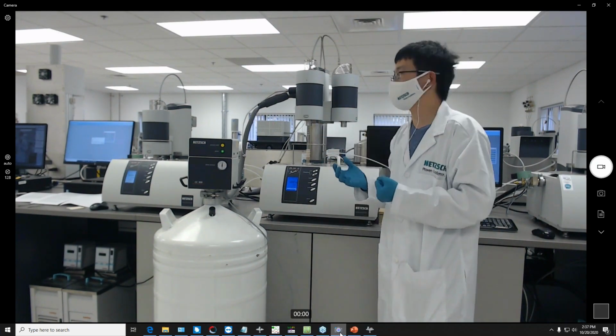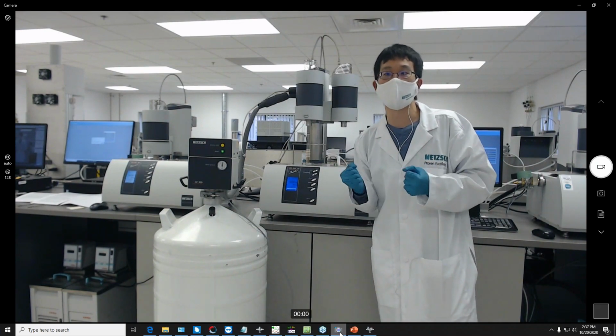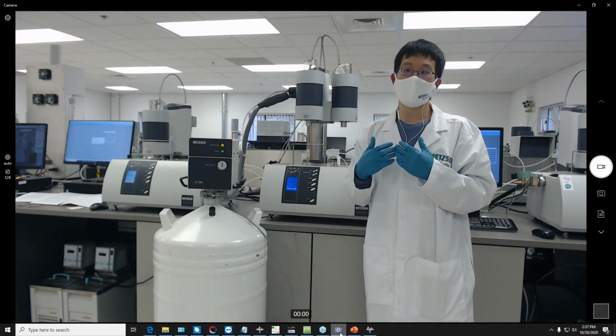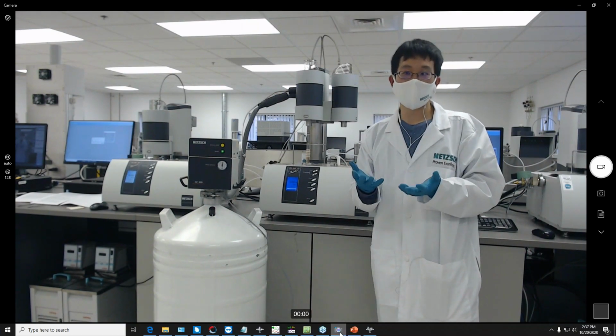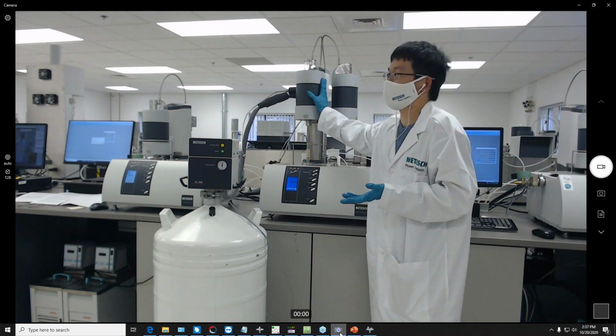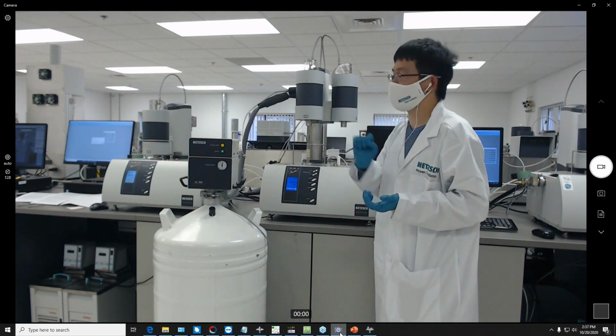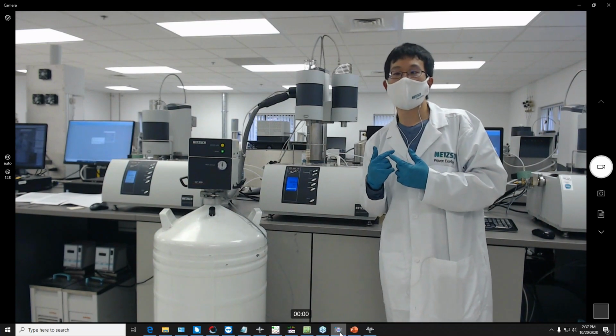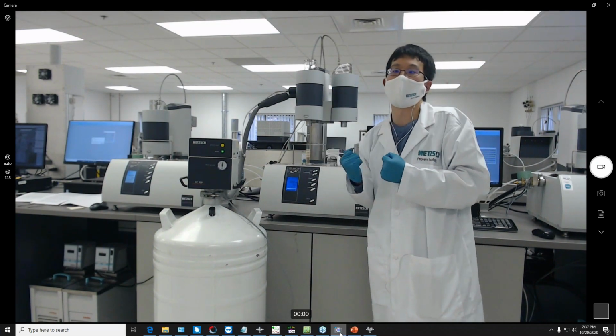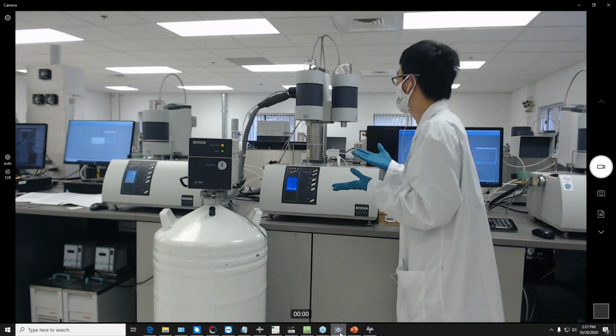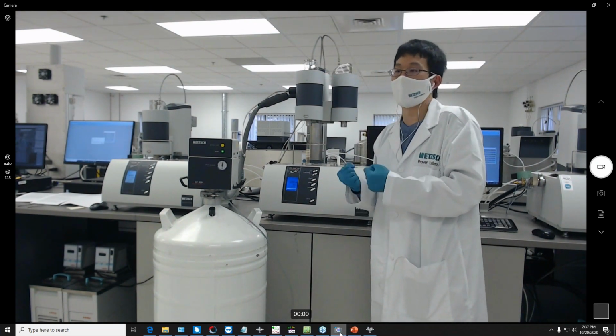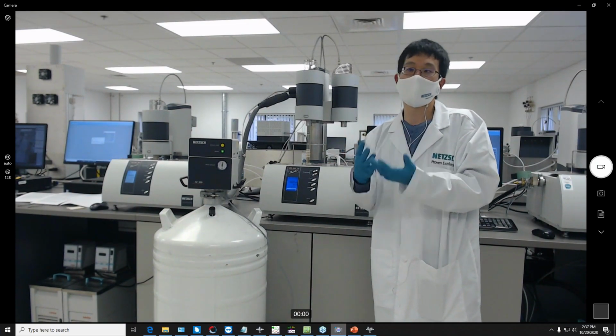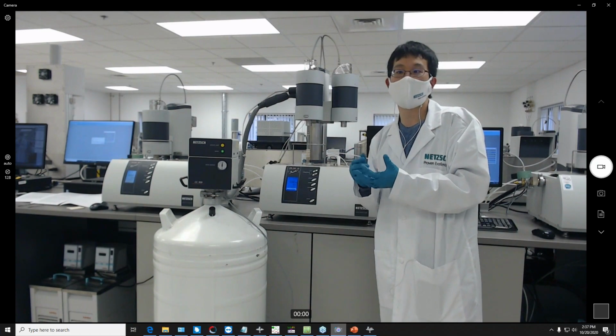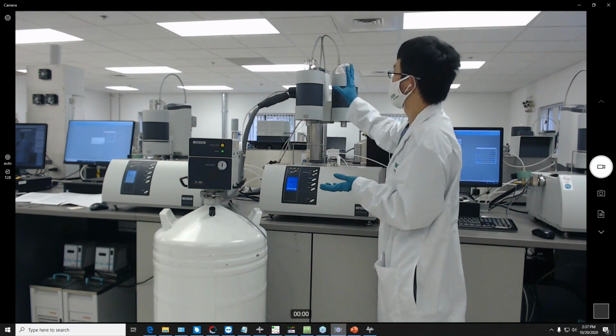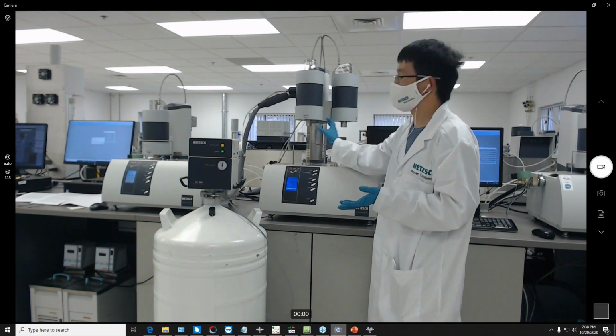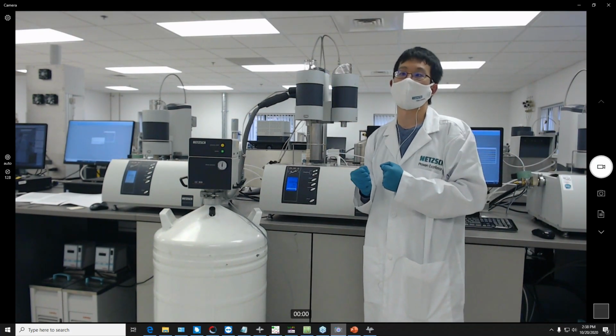So the way that we mitigate that is to operate with STC off so that you don't get those large thermal lags. The STC uses the furnace thermocouple, and because there's a little bit of a thermal gradient to the sample carrier, we usually have to program a little bit higher than the target temperature that you want. So if you want to go to 800 degrees Celsius at your sample level, and we have STC off, we may need to program our temperature program to be 850 with STC off. So our heating element will be at 850, and our sample carrier might just be reaching 800 at that particular point.